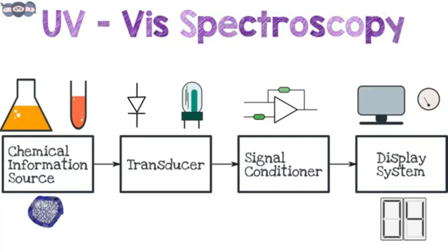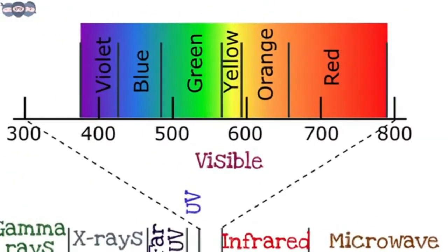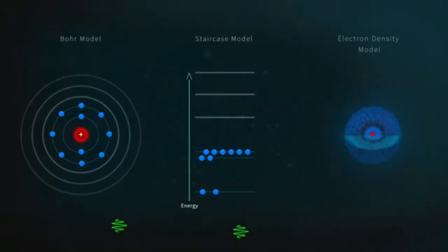To explain the particular influence of the Gd ions on the glass network's light absorption, UV-Vis study offers insight into the wide wavelength range where the material absorbs light the most. An intense blue shift can be observed as the Gd amount increases between 200 to 400 nanometers, showing that our material intensely absorbs UV light.